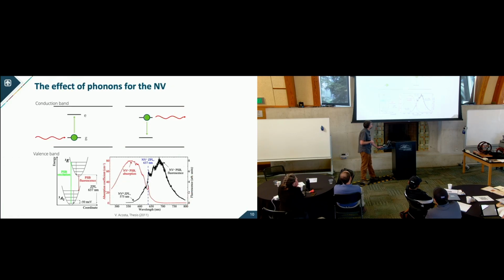Okay, so with a little bit more detail about the solid state, I had shown a very simple picture where you can excite from a ground state to an excited state and then release a photon. Well, that's actually a bit more complicated here. The levels that I showed are this 637 nanometer zero phonon line. And in both the ground and excited state, you have these extra phonon levels as well. So you can actually absorb non-resonant light, so higher energy photons, and then even emit lower energy phonons.